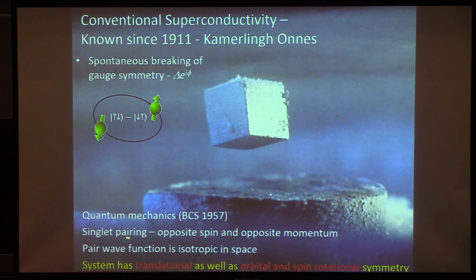So similar to the magnetic system, this system has a lot of symmetries associated with the ordered state, in particular singlet superconductors. And when I refer to singlet superconductors, I refer to the nature of the pair wave function. It is basically very highly symmetric in the sense that the pair wave function is translationally invariant. There is no particular spatial order to this order parameter. It has also orbital symmetry. It doesn't matter how you look at this pair. It still has zero angular momentum, zero projection of its angular momentum, and it has no net linear momentum.